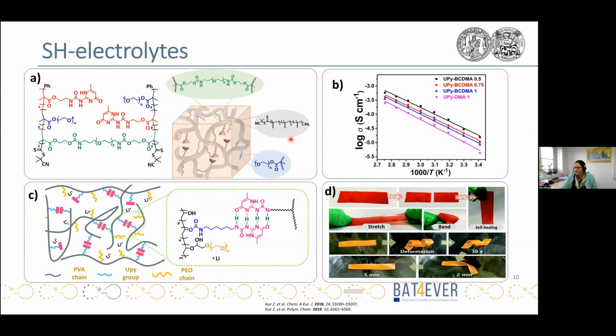Here is one example of the solid polymer electrolyte. We have a copolymer where we have polyethylene glycol groups to increase the lithium ion conductivity. We have the UPy groups for the supramolecular network, but then also a dual network is formed via chemical cross-linking of the polymers, which significantly increases the mechanical stability of the polymer. However, only 10 to the power of minus 5 Siemens per centimeter ion conductivity could be reached.